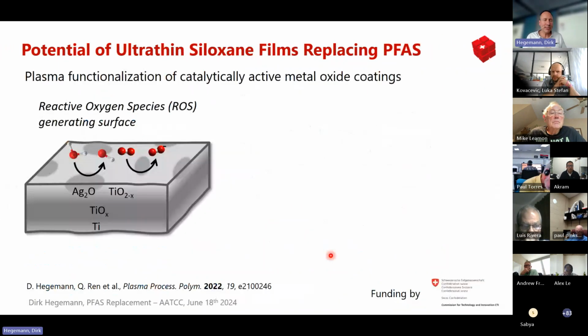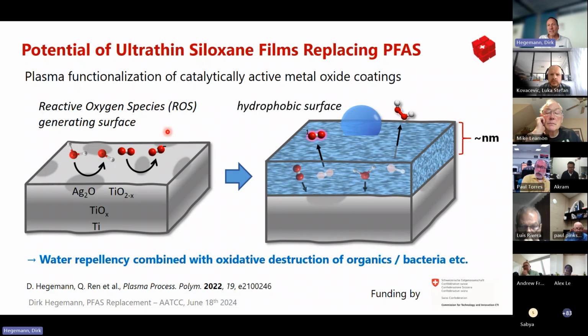Let's look at a few other possibilities. So this was so far simply, let's say, a replacement by a hydrophobic coating to improve the effects. We are looking at catalytic active surfaces. They can also be very, very thin, deposited by plasma. It's a silver doped titanium oxide, and in interaction with water and oxygen, it's producing reactive oxygen species. And we can maintain this catalytic effect by putting a very thin hydrophobic plasma layer on top.